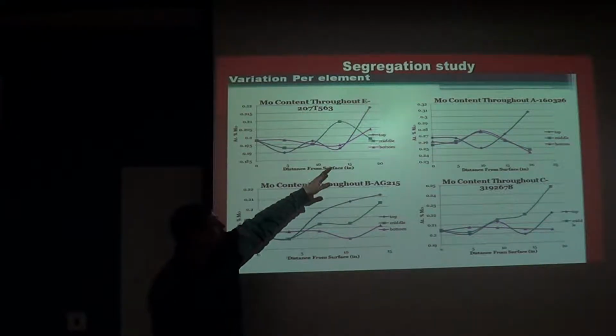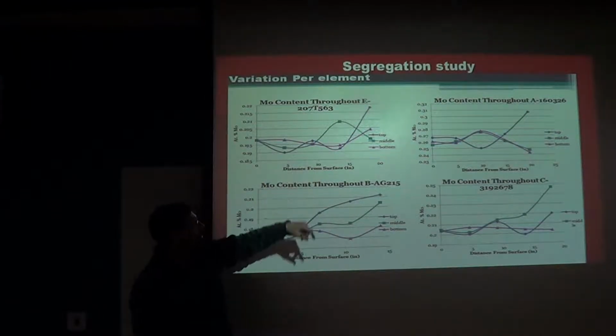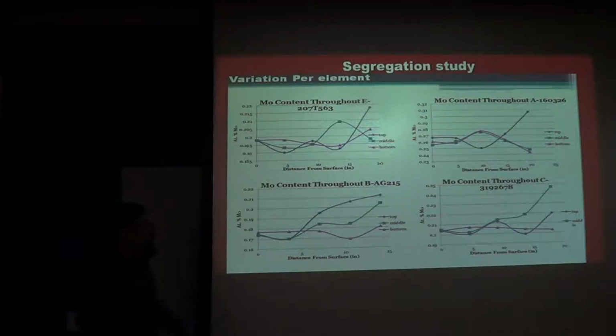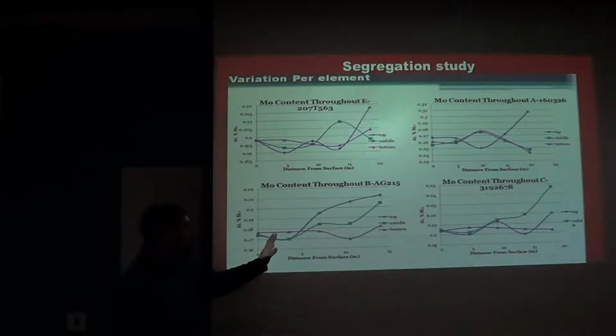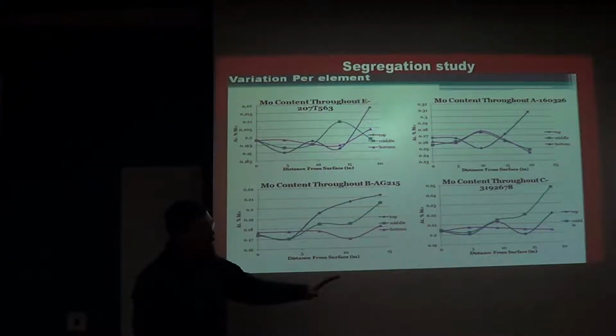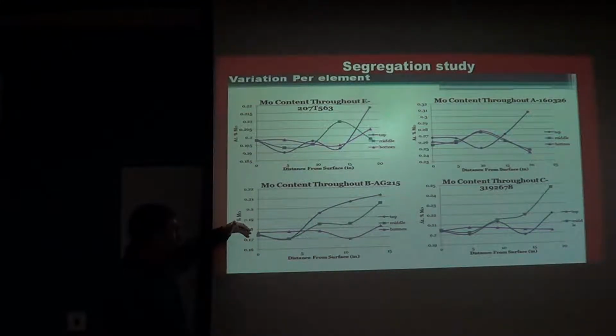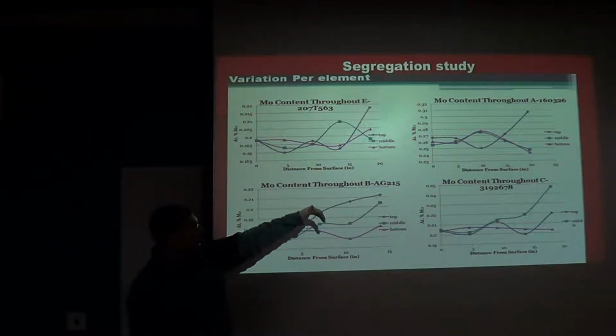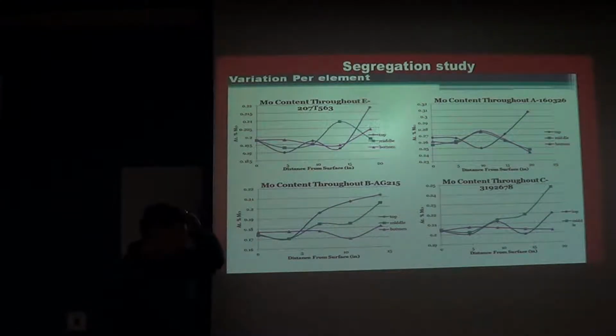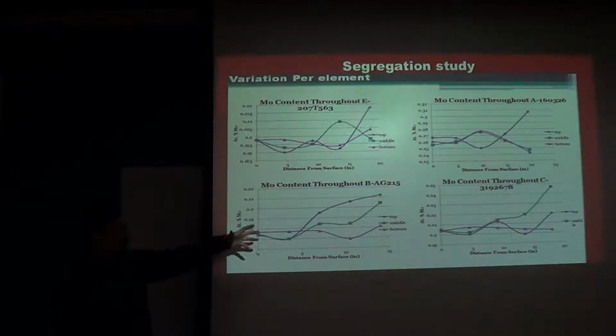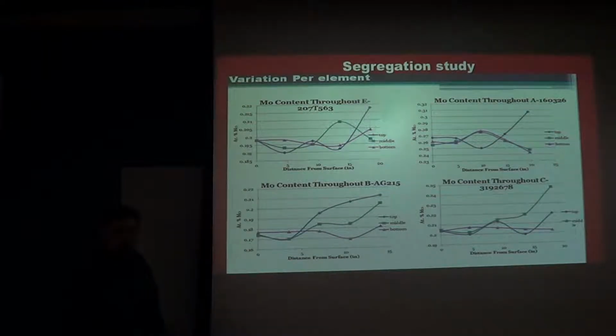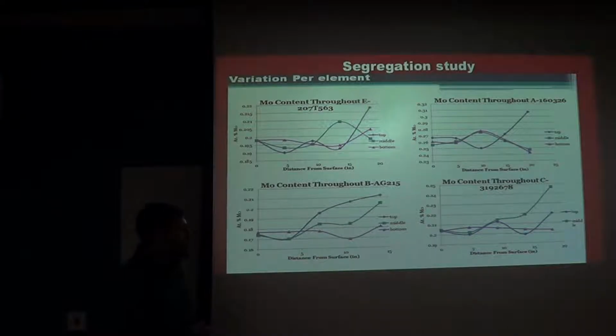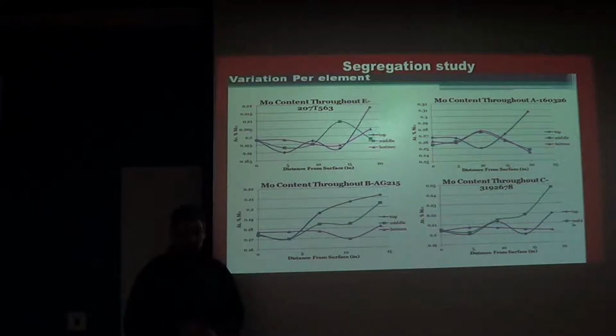and as we move from the surface towards the center, it starts to bounce all over. And we see that different mills, overall, had kind of the same behavior. It was lower near the surface, higher near the center. That was a consistent behavior across the board, but the actual amounts varied depending on the mill, how much they started with. So this was for molybdenum, which is actually a fairly large atomic radius element, one that we wouldn't expect to do a lot of segregating.